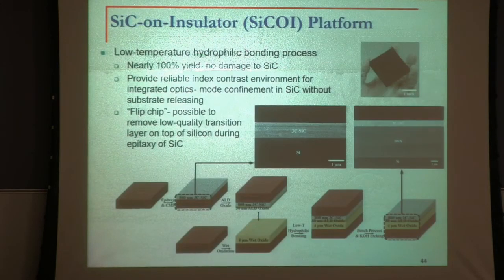So what did we do? If you look at silicon carbide, it's usually grown on top of silicon, but you cannot make devices in it because the index of refraction of silicon carbide is lower than silicon. It's about 2.1, 2.2. Silicon is 3.3. So light will go all into silicon. So you have to remove silicon somehow, and people undercut or do some other things. When we started this research, the quality factor of resonators in silicon carbide was very low. Part of the reason is that the stress at the silicon carbide will result in low quality of the film in here and a lot of scattering, so you get a lot of loss.